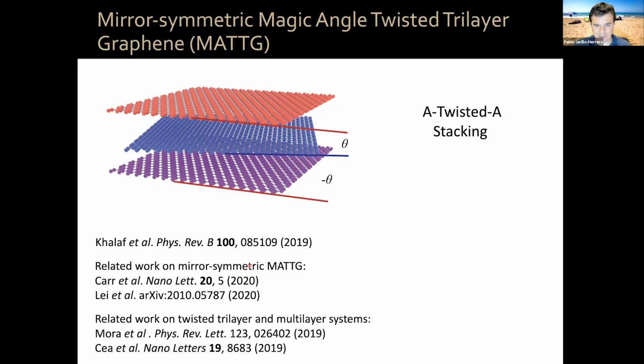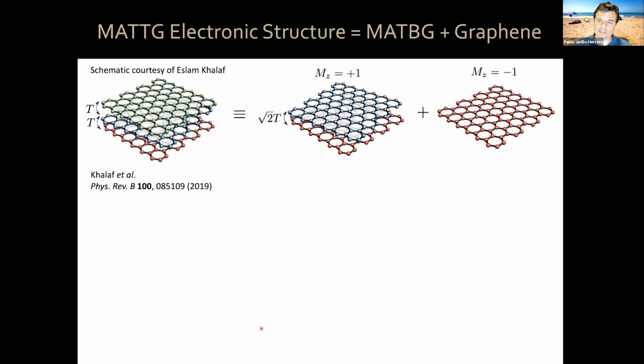Now, plenty of other work related to mirror symmetric MATTG has been published, and related work on twisted trilayer graphene and multilayer systems too. Now, this system, magic angle twisted trilayer graphene, has a very interesting electronic structure. If you think of these 3 layers with interlayer tunneling T between the layers, it turns out you can make a rotation, a basis transformation of the Hamiltonian of this system, such that it becomes block diagonal, where one block is a magic angle twisted bilayer graphene-like block with an effective square root of 2 times T interlayer tunneling, and the other block is just a monolayer graphene block.